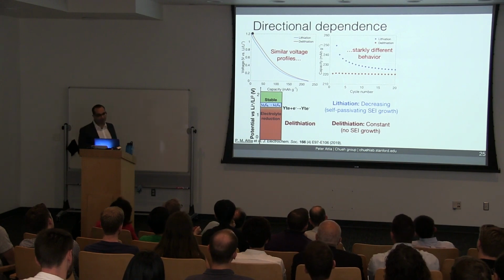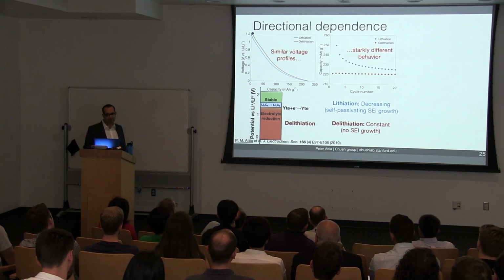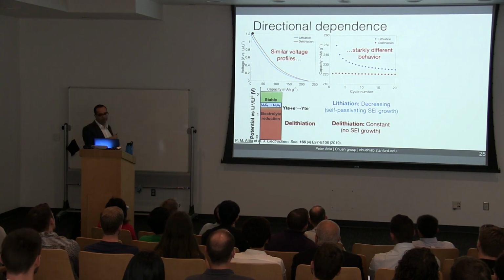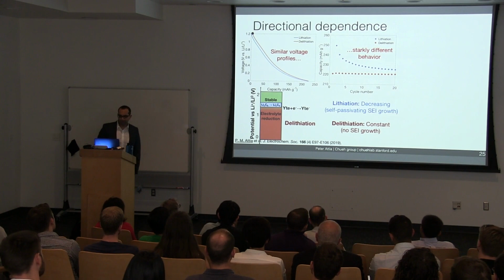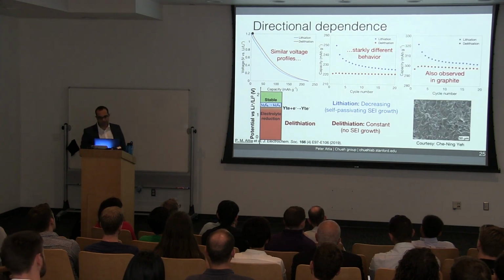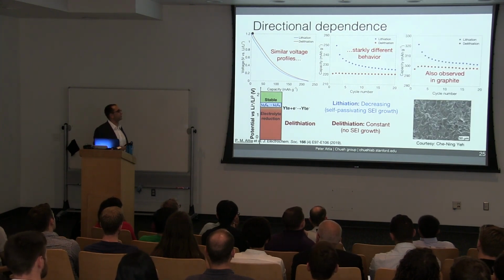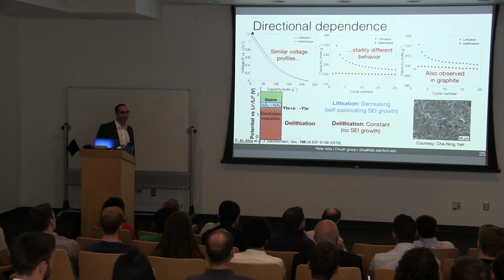But we saw that SEI only grew during lithiation. In fact, we can see that even just from the capacity curve of carbon black. Capacities during lithiation are decreasing, indicating cell passivation. But in contrast, the capacities during delithiation are constant, which indicates no SEI growth. I also want to mention briefly that a lab mate recently also saw the same effect in graphite. So this directional dependence isn't just some weird fluke of carbon black.